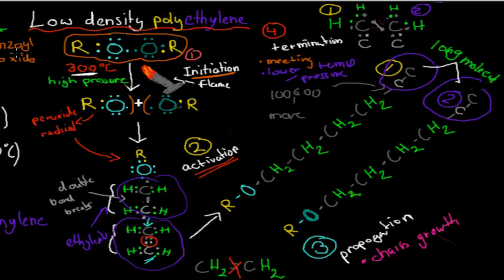To summarize the procedure: we started with benzoyl peroxide, used high pressure and 300 degrees Celsius in the initiation stage to break it apart into peroxide radicals. The peroxide radicals attacked one of the ethylene structures to get back to the magic number of eight — that was the activation stage. The ends of each ethylene structure were then missing an electron and attacked another ethylene, causing more and more chain growth — the propagation stage. When chains met, they shared electrons making them neutral, which terminated the growth. Or the temperature and pressure were lowered, ending the procedure. Remember those four steps: initiation, activation, propagation, and termination.